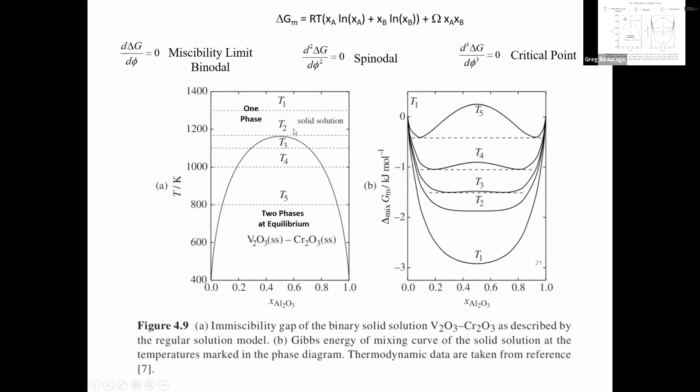So when you get to this critical point, the weird thing is the free energy goes flat, right? That means if I throw in a composition of 0.4, and then I allow fluctuations to happen, it's going to go left and right. So I make two phases, one to the left, one to the right. Nothing's changed, the free energy didn't change any. There's no selector for whether it phase separates or not. It's like crazy land, it can do anything at once. So any fluctuation could possibly exist or could possibly not exist. So there's no predictability at the critical point.